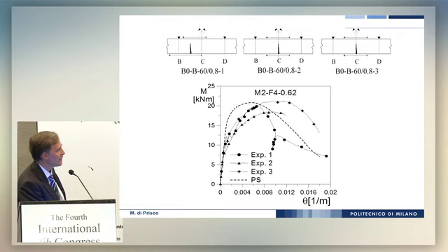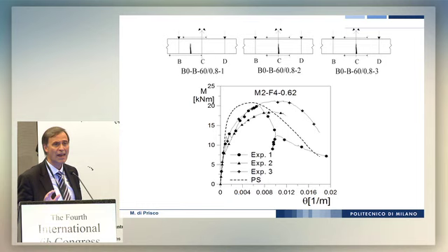So if we adopt the plane section model, that means essentially the conventional model we have in the Model Code, we can follow this dashed curve in terms of bending moment versus average curvature. If you measure the curvature related to this crack, you have this difference in the three beams we tested. We are working on the average values, without any safety, without any characteristic computation, just the average values, and it seems quite realistic.